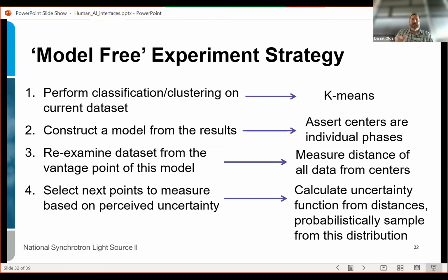It's great. We construct a model from the results. So we asserted that the centers of the k-means must have been the individual phases. We re-examined the data set from the vantage point of the model, which really just means classifying all the data sets we've measured so far in terms of their distances from the centers. And then we selected the next points to measure based on the perceived uncertainty in this model.